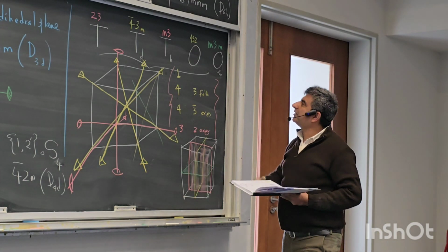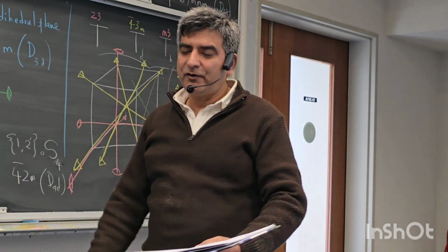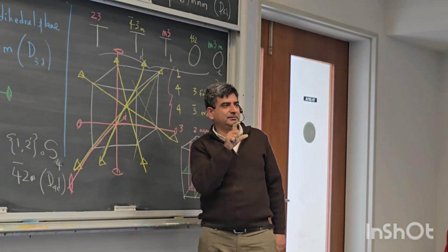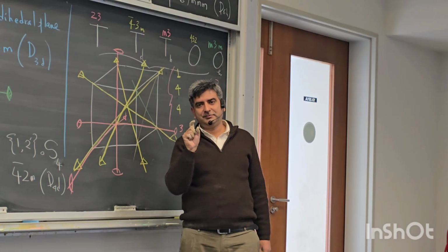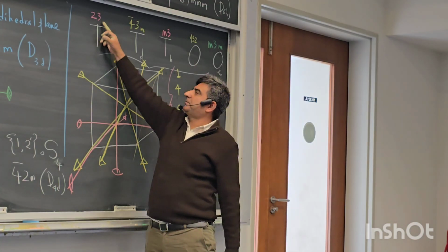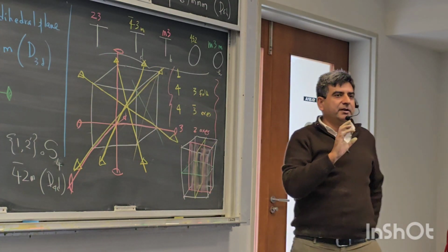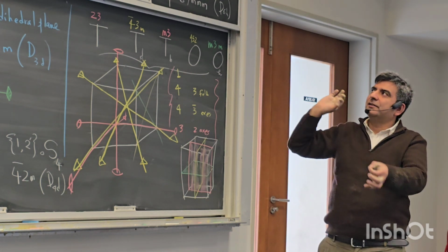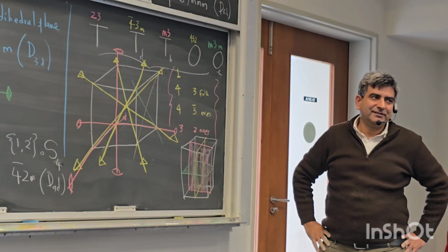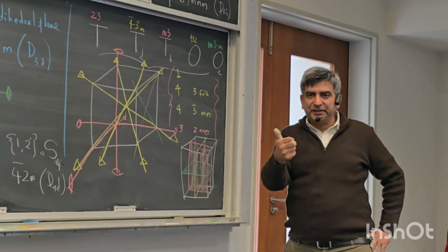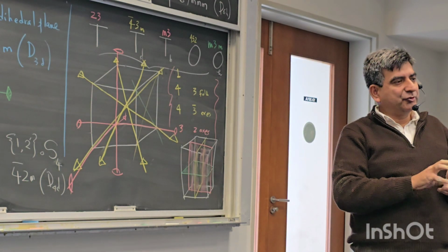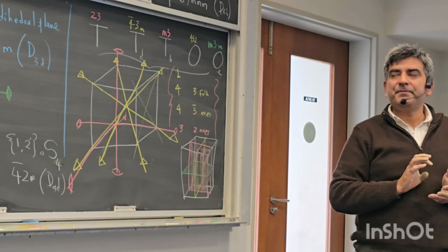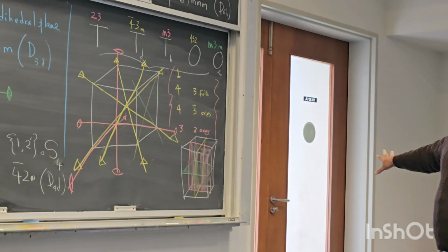Okay. Notice that in all 5 of these cubic point groups, there is this number 3 in the middle. Number 3 at position number 2, which represents a 3-fold axis of rotation along the body diagonal. Okay, so this is a quick check to see whether that point group belongs to the cubic class or not. Okay, so these are our 32 point groups.